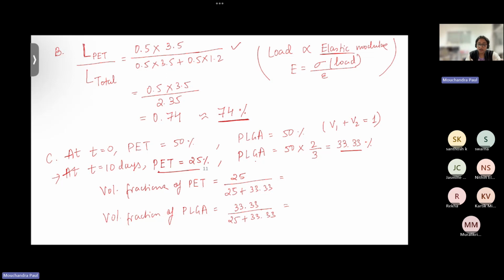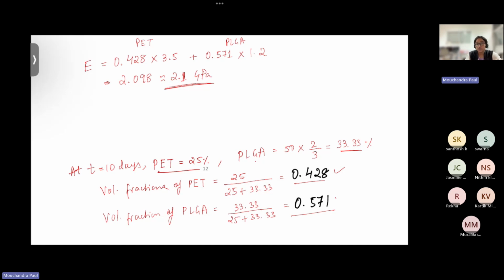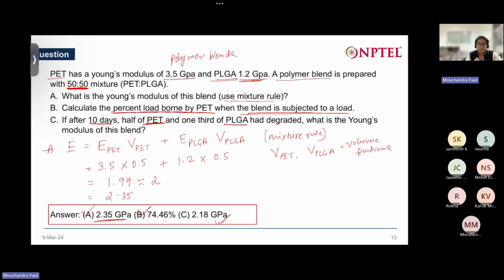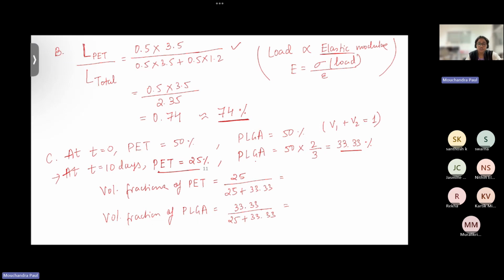And in part C, we were told that half of the PET was degraded, whereas one third of the PLGA was degraded. Now for the remaining polymer blend content, we have to determine the elastic modulus. So first we have to find the new values of volume fractions in this polymer blend, and using these new values, we have to calculate the elastic modulus for part C. Now if you note, the value of elastic modulus after degradation has decreased. It is lesser than the initial one. Initially we got 2.35 gigapascal, but now it has reduced to 2.1 gigapascal. So it has happened due to degradation. This type of logical reasoning you can do with yourself when you are solving such problems on your own.